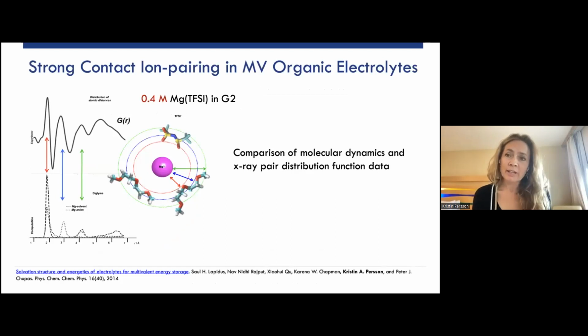So the first thing we did when we started looking at magnesium and calcium electrolytes, almost 10 years ago now, was collaborating with a group at the Advanced Photon Source in Chicago, where they were doing X-ray pair distribution measurements. We were doing molecular dynamics, and we found that there was a really nice agreement between what we were seeing and they were seeing, which led us to the conclusion that in fairly low molarity magnesium electrolytes, so this is 0.4 molar magnesium TFSI, and we normally don't think of TFSI as a highly coordinating salt anion, in diglime, we found that the majority species was actually contact ion pairs. So the species that I'm showing here is magnesium coordinated by 1 TFSI and 2 diglime. That was found by both simulation as well as experiments to be the dominant species in the bulk electrolyte. So what are the implications of this?